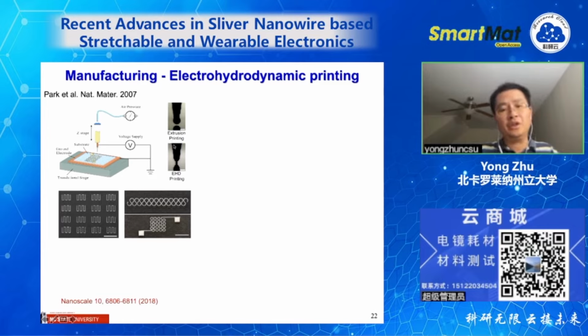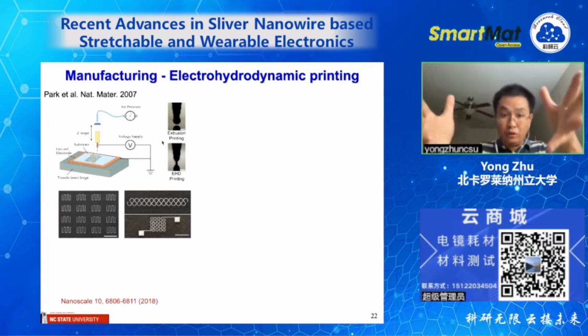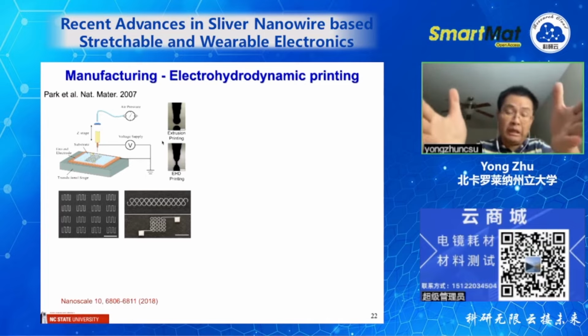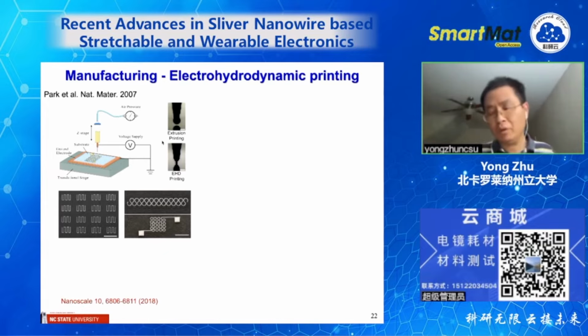This will be the inkjet. The problem with inkjet is the nanowires. It's good for printing, let's say, commercial inks, typically made of silver particles or flakes. But with nanowires, these wires are long, 20, 30 micrometers or even longer. Remember, we said the longer may be the better in terms of stretchability. We want them to be long, but then it causes problems. They could clog the nozzles. If the nozzle is small, you want high printing resolution, so you cannot have too big a nozzle. So that's the dilemma, and we can approach this problem using this method.